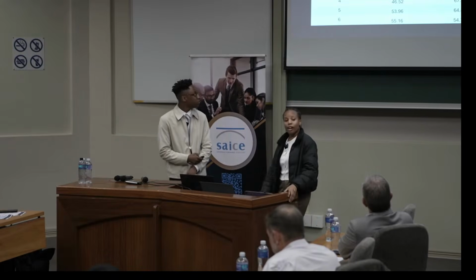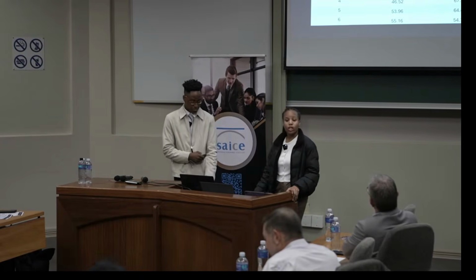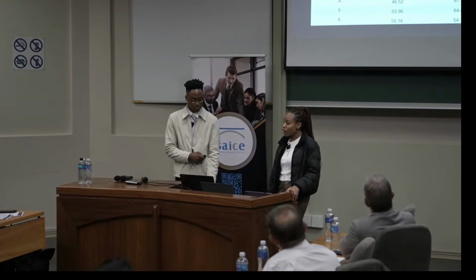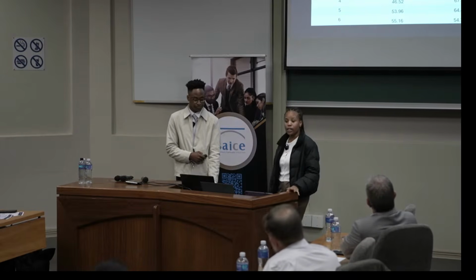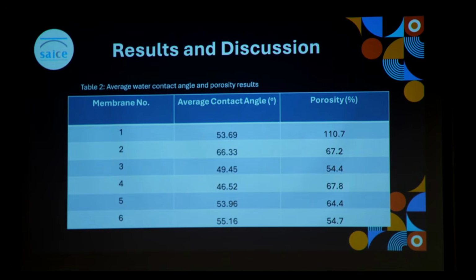Turning our attention to the characterization of the membranes, several important trends were observed. The water contact angle results showed that all the membranes were hydrophilic, with values below 90 degrees confirming their suitability for desalination. Interestingly, the introduction of a PIL produced a nonlinear effect on hydrophilicity. Small additions of the PIL initially increased the contact angle, but further incorporations in membranes 3 and 4 significantly reduced it, indicating improved hydrophilicity. This aligns with literature showing that lower contact angles are associated with better antifouling performance.